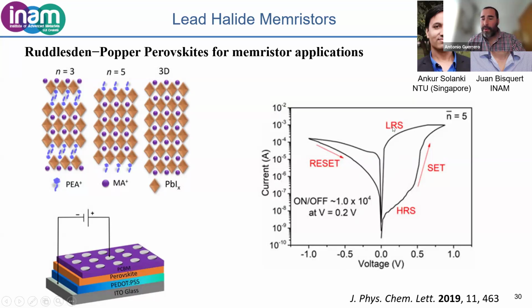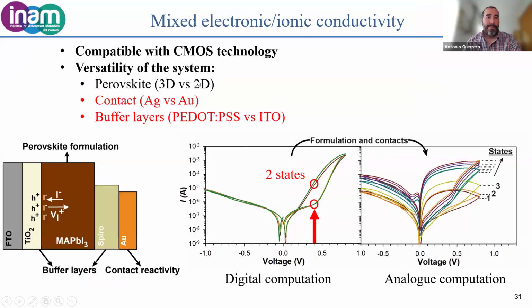And at the time, we had very good response with very large on-off ratios, so between the high resistive state and the low resistive state, but we didn't understand very well the system. But now we do understand the system. We can change the system to have only two states, which is typically used for digital computation, or we can have multiple states, which is also useful for analog computations. And we can go from here to here by modifying the composition of the perovskite, by modifying the contacts, and by modification of the buffer layers.